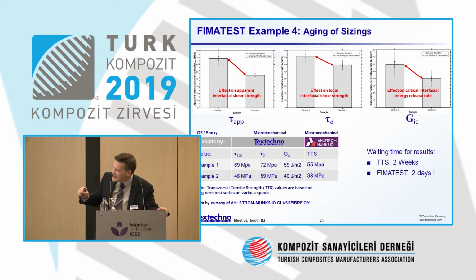This is an example that we've run together with Ahlstrom in Finland, and they were performing a transverse tensile test, TTS, and we did it on 2 samples. This is these 2 rows in the table down there, and the one glass fiber was fresh, and the other one was an aged glass fiber. And you see how in the transverse tensile strength test, the shear strength is dropping from 55 megapascal to 38.